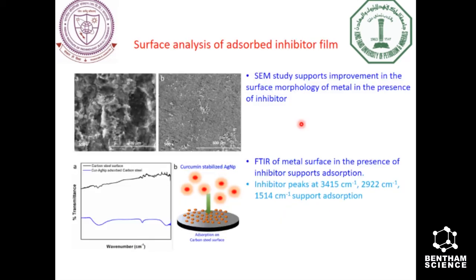Then the surface analysis of the adsorbed corrosion inhibitor film was carried out using scanning electron microscopy and Fourier transform infrared spectroscopy. And an improvement in the surface smoothness in the presence of inhibitor film supported the inhibitor adsorption. And the characteristic peaks of the corrosion inhibitor at 3400, around 2900, and around 1500 per centimeter supported the inhibitor adsorption on the metal surface. This picture shows a tentative schematic of the adsorption of the inhibitor on the steel surface.